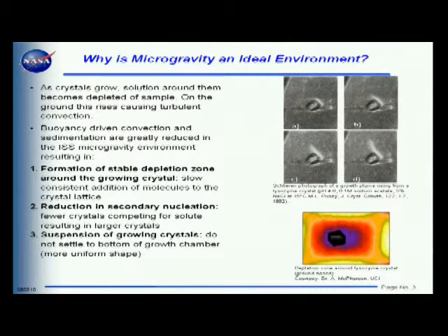And what that in turn does is now, instead of that crystal surface being exposed to a region of low concentration, which gives a diffusion-limited growth rate, it is now subjected to the higher supersaturated concentrations, which will, one, cause rapid growth, and two, enable misoriented molecules to be trapped into the crystal lattice, thus you have a lower quality structure.